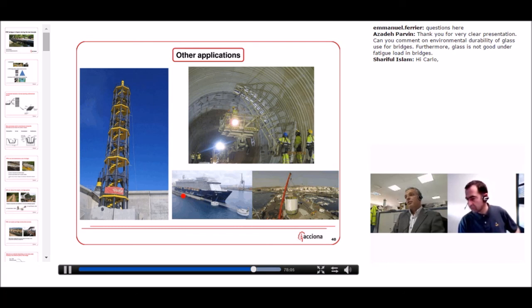Concerning the use of glass fiber under fatigue, we have performed tests on fatigue, on a reduced scale model of the girder, and what we observe is that actually it doesn't have a critical issue concerning fatigue for bridges. We didn't observe this in our tests.